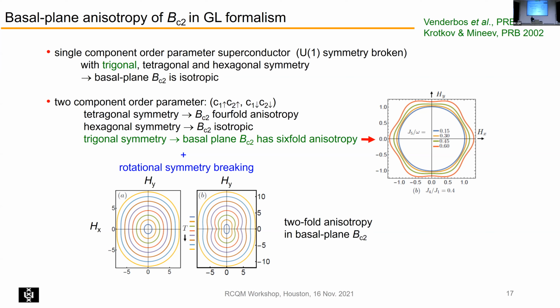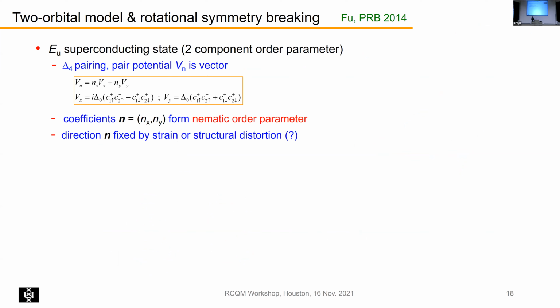Now we can do one step further, and we can go back to the Eu representation and write this pairing potential as this. So now we write it as a vector here, and there are these 2 components, eta x and eta y, and they were actually given the name by Liang Fu as the nematic order parameter. And then the idea is that that could point in 3 directions, but apparently the crystal selects only one of these directions, and that is maybe due to strain or structural distortion. And so you get this picture.